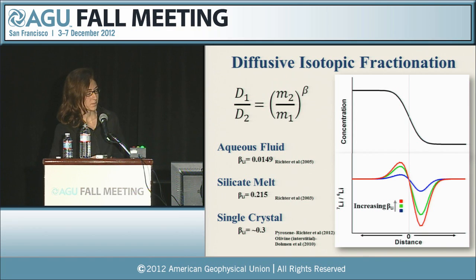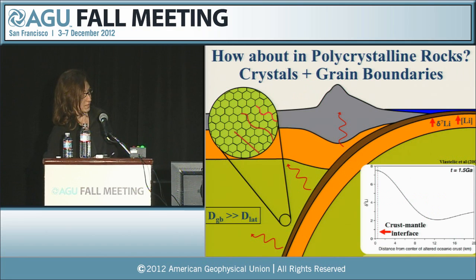So for lithium, beta values have been measured in aqueous fluids, silicate melts, and single crystals. In aqueous fluids, it's about 0.015, silicate melts about 0.2, and in single crystals, it's about 0.3. So what about diffusive isotopic fractionation in polycrystalline rocks? In this case, the lithium would diffuse both through the crystals and the grain boundaries. One instance where this may be applicable is when an oceanic slab is altered by seawater.